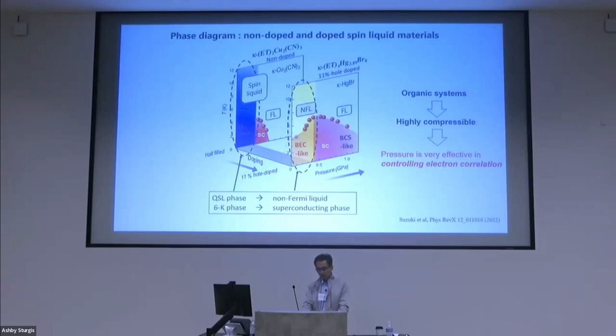However, as I'd like to show you from now on, this phase is a non-Fermi liquid, and quantum criticality is shown in this phase. And the superconductivity appears at a temperature here, and in this region the superconductivity shows BEC-like behavior, and then as a function of pressure, the behavior crosses over to BCS-like behavior. So we think that this BEC-BCS crossover is driven by pressure. Okay. From now, I'd like to show you some experiments.